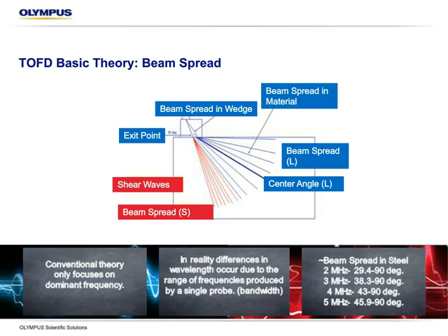in two different ways. First of all, when we pulse the instrument, the sound goes through the wedge. We have beam spread that occurs inside that wedge. And then once that sound goes through the coupling material into the actual material we're testing, we get another effect of beam spread. So we actually get a good manipulation of beam spread, which allows us to use a very small transducer and get a very wide volume of coverage, which is very useful and one of the main benefits of time-of-flight diffraction. We also have different wave modes. So we can see here, if we use TOFD, we're using longitudinal waves.